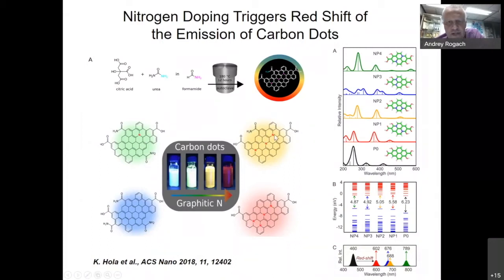And actually, if nitrogen is graphitic, which means it is built into this graphitic lattice, like for the orange and red emitting carbon dots, then it is better to shift the emission to longer wavelengths. And if nitrogen is at the border here, or there is very little graphitic nitrogen, then the emission color will be blue or green. But if we do so, we already receive what we want. We receive full color tunability for their emission.